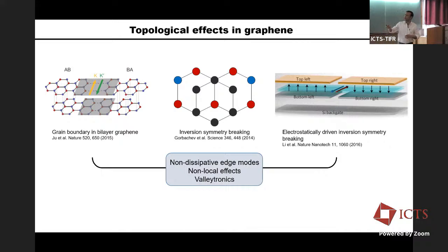For example, you can apply a potential from, say, boron nitride or some other material, and lead to inversion symmetry breaking of the graphene lattice. That leads to another set of different topological state. People have looked at it from electrostatically driven by applying two opposite electric fields. Also, it has led to inversion symmetry breaking and new topological phenomena.